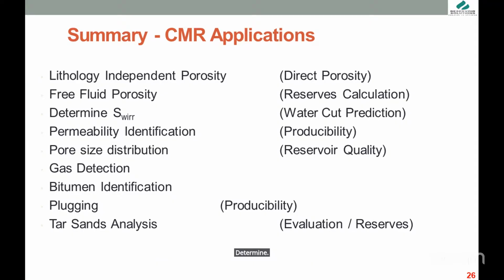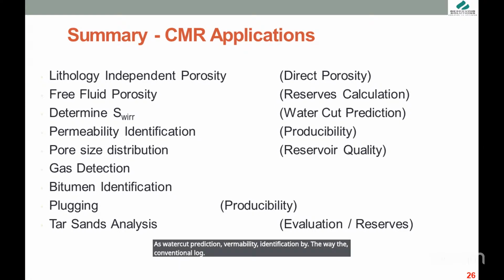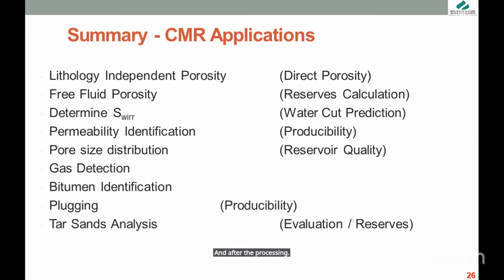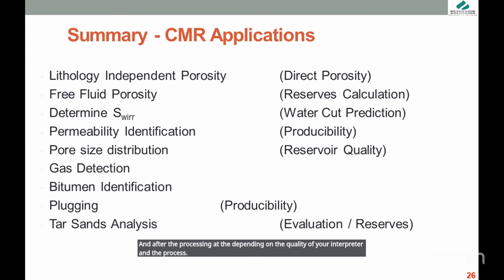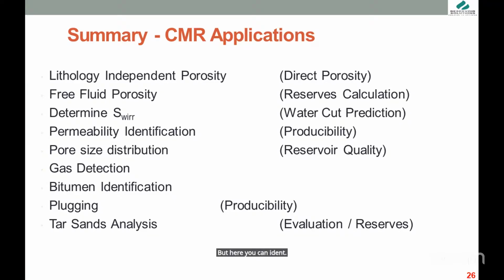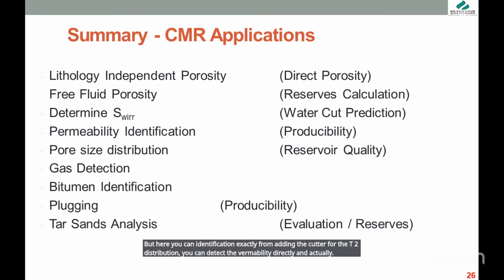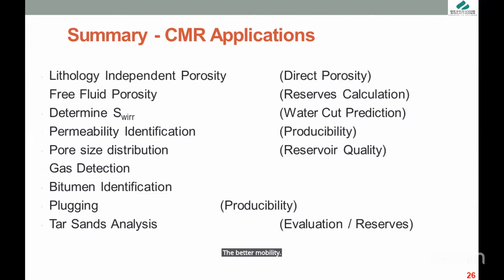Determine the water saturation, water cut prediction, permeability identification. By the way, the conventional logs cannot estimate the permeability. The only conventional tool that can estimate the permeability is the Stoneley from the dipole sonic image or sonic vision, and actually it's an advanced tool as well, after the processing, depending on the quality of your interpreter and the processing center. But here you can identify it exactly by adding the cutoff for the T2 distribution, and you can detect the permeability directly. And actually, this is the producibility, the permeability that you should use during the production.